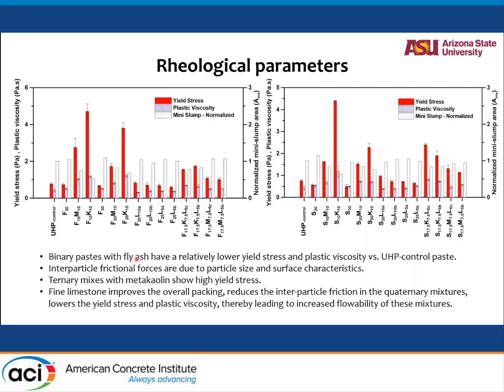Binary paste with fly ashes were found to have relatively lower yield stress and plastic viscosity with respect to control paste, because of interparticle frictional forces. Metakaolin shows higher yield stress, obviously, because it's a much stickier clay-like material. Fine limestone was found to improve overall packing and reduce interparticle friction in the mixes with quaternary binders, and lowers the yield stress and plastic viscosity, leading to increased flowability, something that we always found very beneficial with the use of limestone in a variety of different types of mixes. And right now we have Portland limestone cements coming out, so it's no more a rarity to have limestone in your concretes anymore.